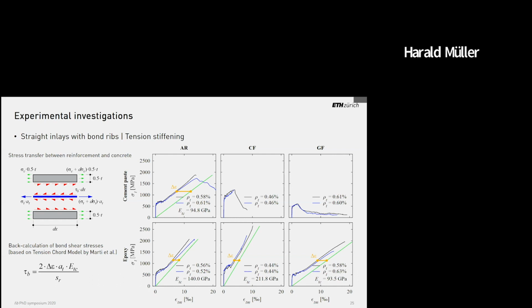The other point, which is surprising, when just looking at the cement paste, is that we have such a pronounced decrease in the maximum load between the aramid and the glass fiber, because the strength difference of the material is, let's say, 30%, but here we have a factor of nearly 3 or 2.5. What's the reason for that?